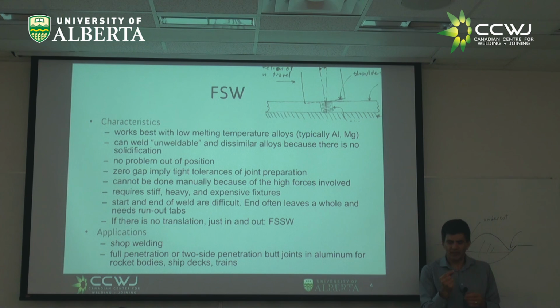So the problem had two stages of solution. One is, how about if you make a tiny weld, a very narrow weld? Here in Canada, people developed a process called variable polarity plasma arc welding, VPPA, that could just do it. The Chinese used that same process to weld their space station, for example. But then there is a second stage of development that was friction stir welding. Today, the body and the tanks of most rockets are welded with friction stir welding. This is pretty cool. It was an enabling technology.